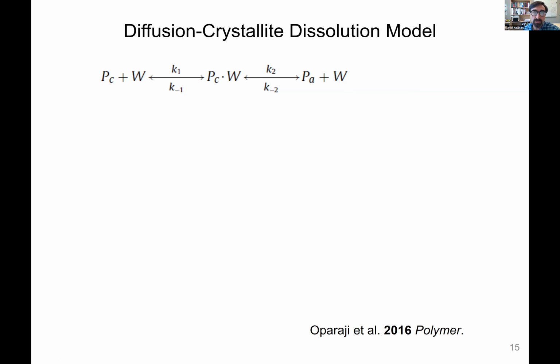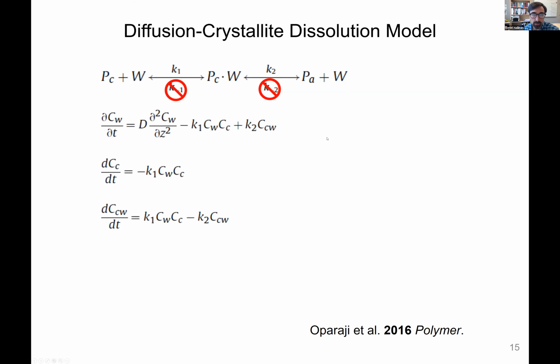Since all of our experiments were sorption, to simplify the model and reduce the number of fitting parameters, we assumed it was an irreversible model, so we don't need to worry about the back reaction rate constants. We just have K1 and K2 as our forward reaction rate constants. We can write conservation balances for each of the components in the system: the water molecules, subscript W, the polymer crystals, subscript C, and then the water polymer crystal complex, subscript CW. The crystals and crystal water complexes are not diffusing, only the water is diffusing. So the rate of change is on the left-hand side of these equations. The first term in the first equation is a diffusion term, and then there are two reaction terms.